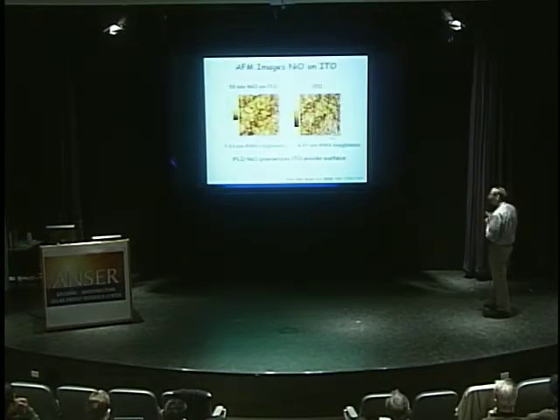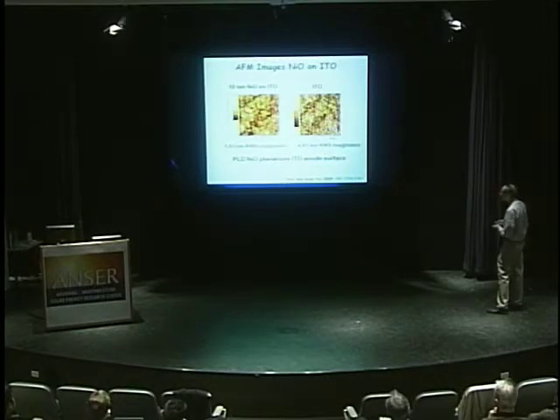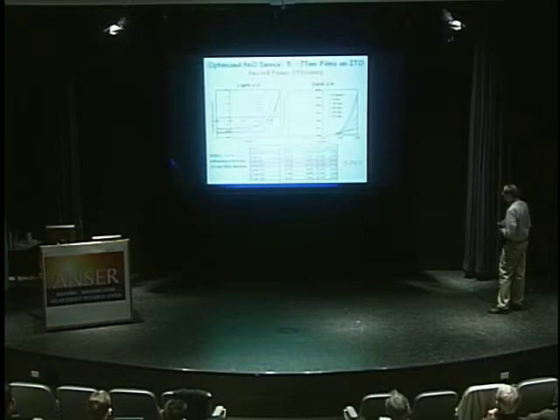So first of all, nickel oxide deposited on ITO, the AFM, and now we have conducting AFM as well, says that if anything, it planarizes the ITO. So the RMS roughness of the ITO drops from about 4.8 nanometers to about 1.5. Let's look at some cells.